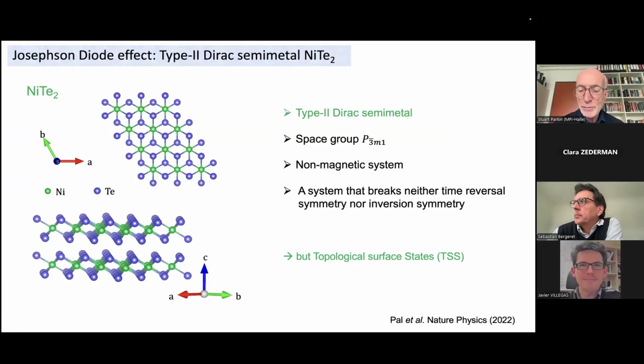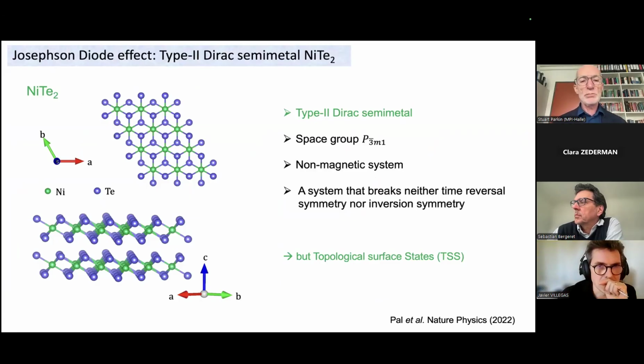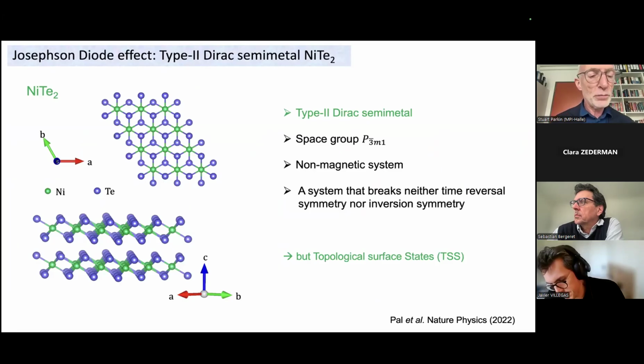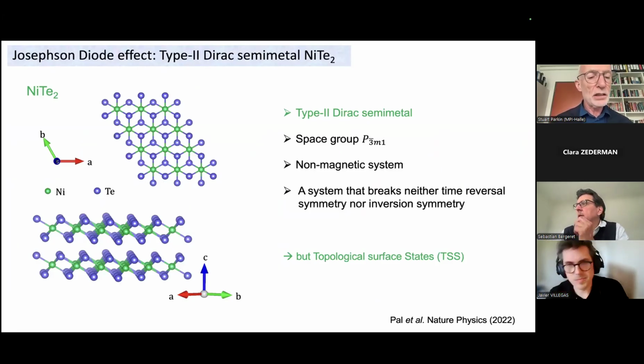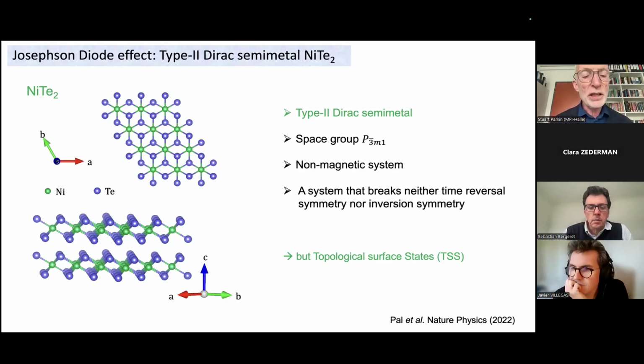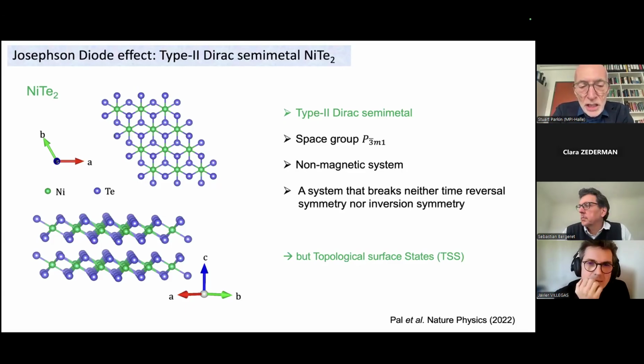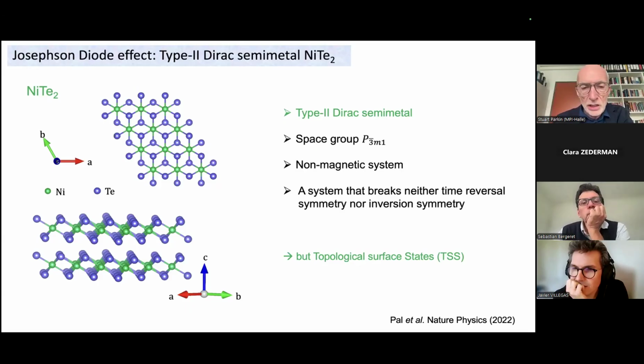And this is some work by Banabir Pal, who was a postdoc in my group at the time. And what we did, we took a so-called nickel ditelluride. It's a 2D system, as shown on the left-hand side. You form these beautiful layers of nickel and tellurium. And the tellurium layers on either side of the nickel layer form this strongly bonded structure, in which the nickel is octahedrally coordinated by the tellurium. But one layer of nickel ditelluride is effectively only weakly bonded to the next, through this so-called van der Waals gap.